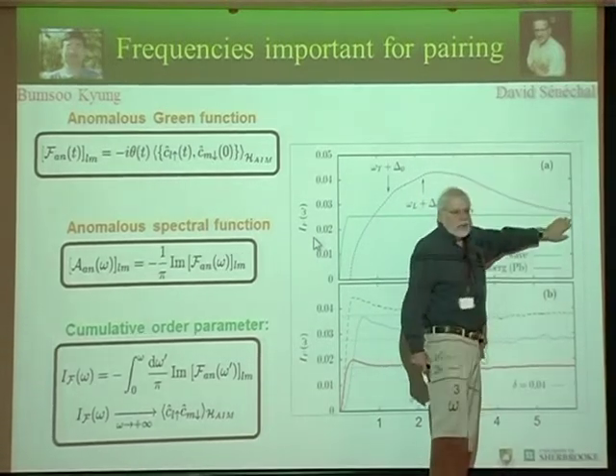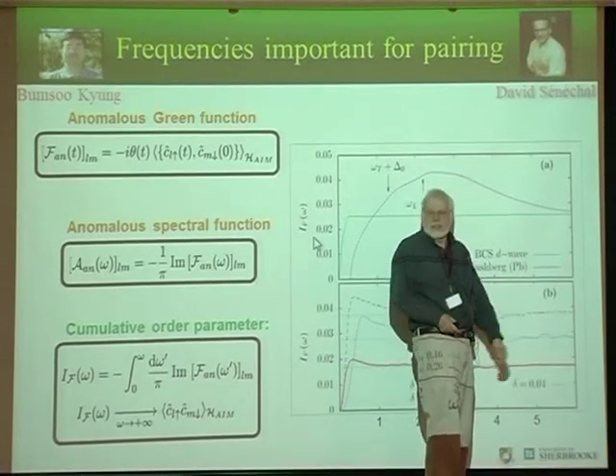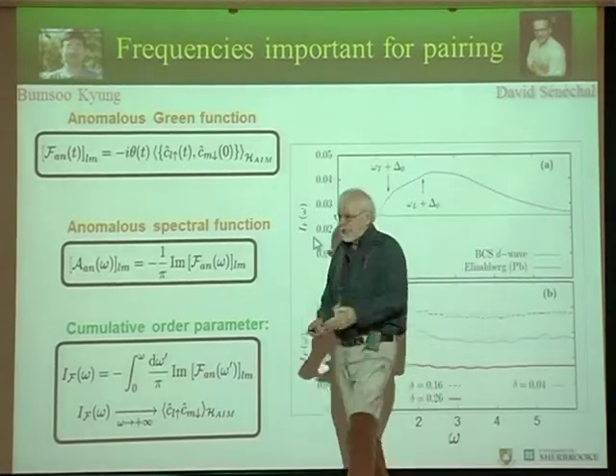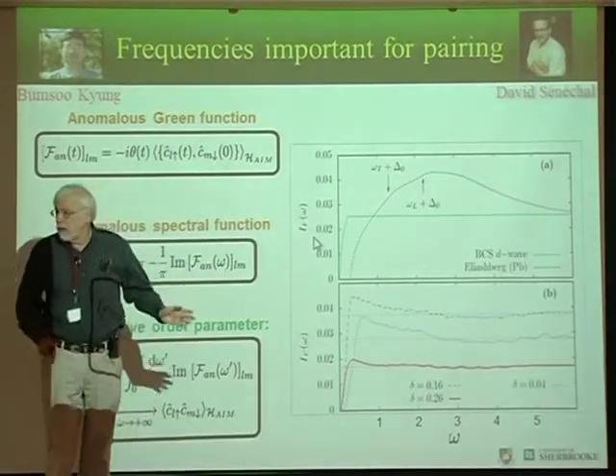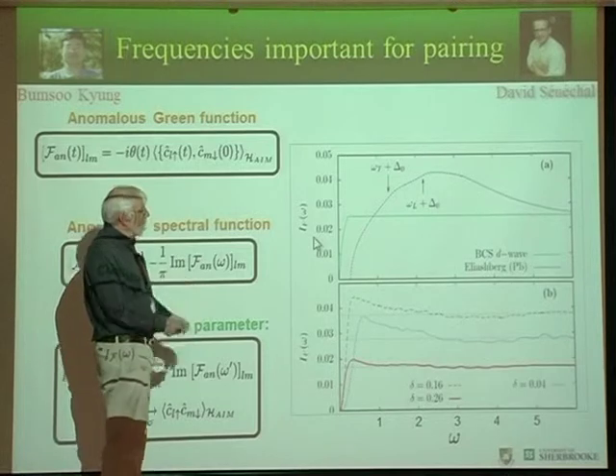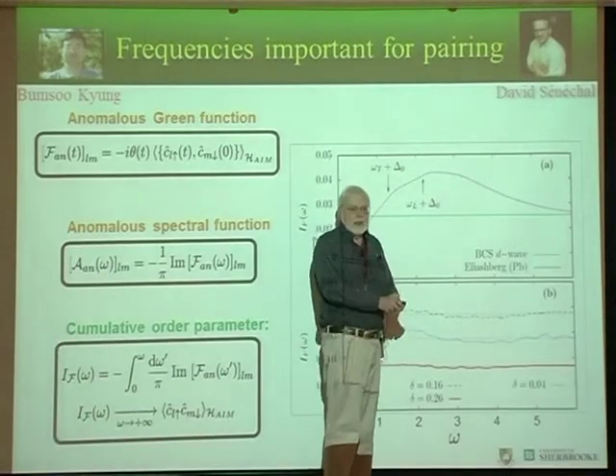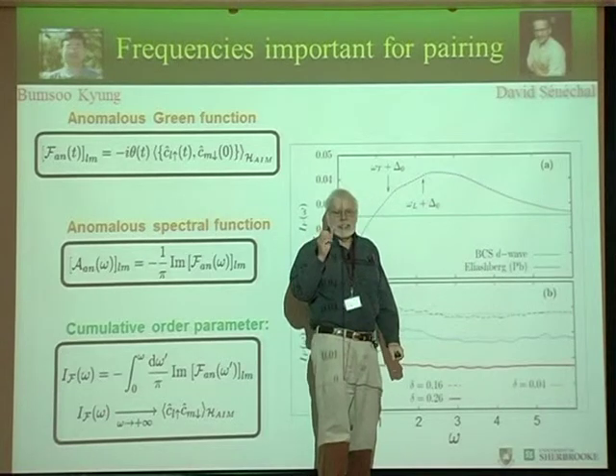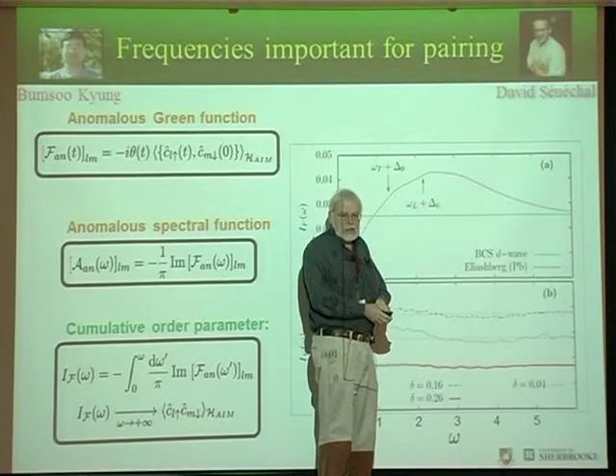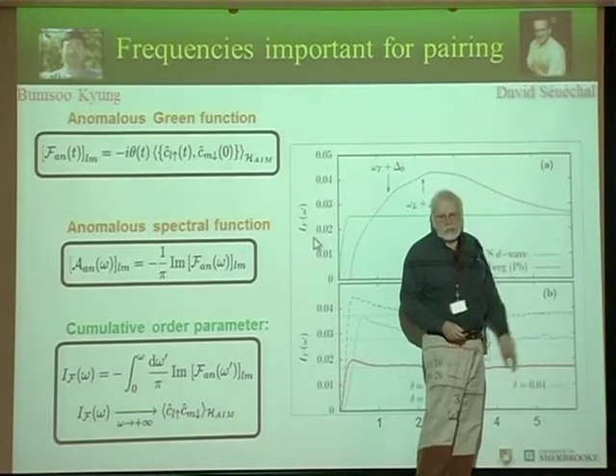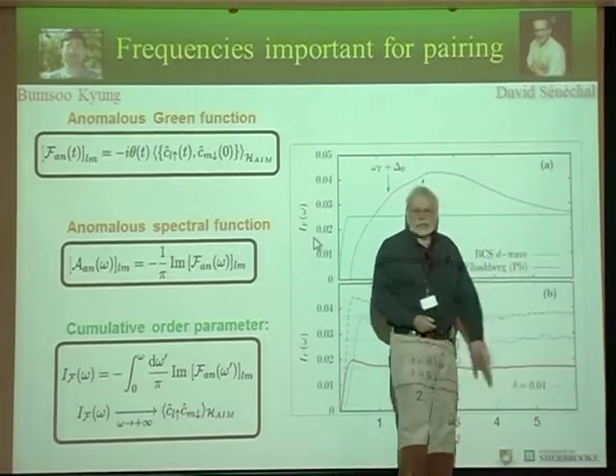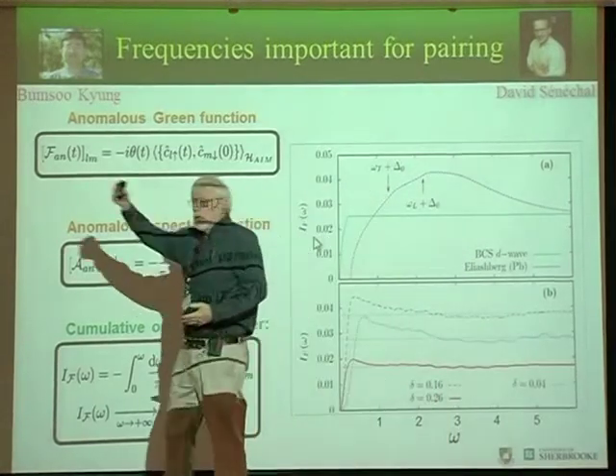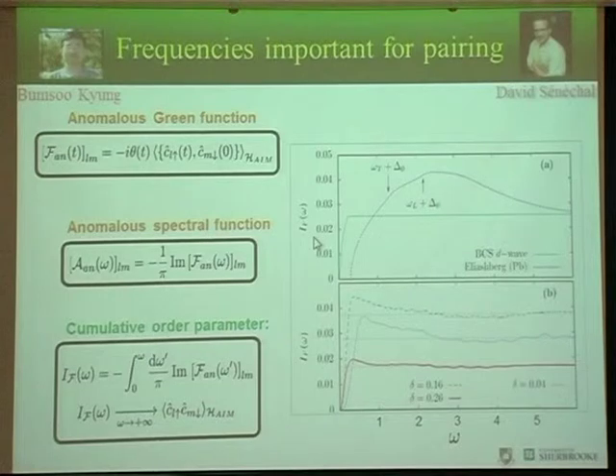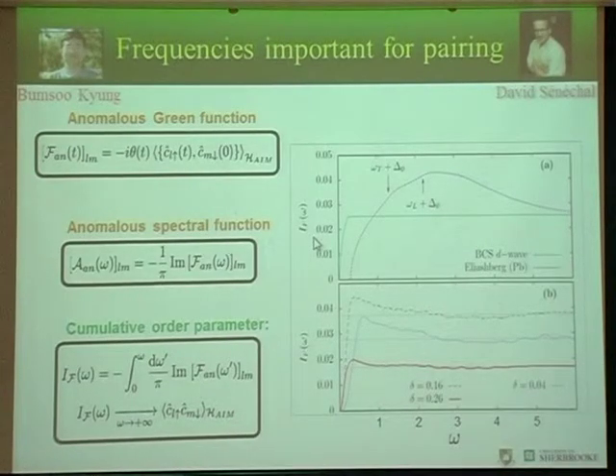It comes down here. So why does it come down? It is this negative part of the anomalous self-energy that I was pointing out earlier that makes this go down. In fact, if you look at the Eliashberg equations, where this comes from, and you remove this so-called mu star, which takes into account Coulomb repulsion, you will find that it is flat. So this going down here is the effect of the Coulomb repulsion. But it occurs at larger frequencies, so it does not completely kill the superconductivity. We know that retardation is important. You don't want the two electrons to be at the same spot at the same time. So you scatter off a phonon, and then another one comes in.